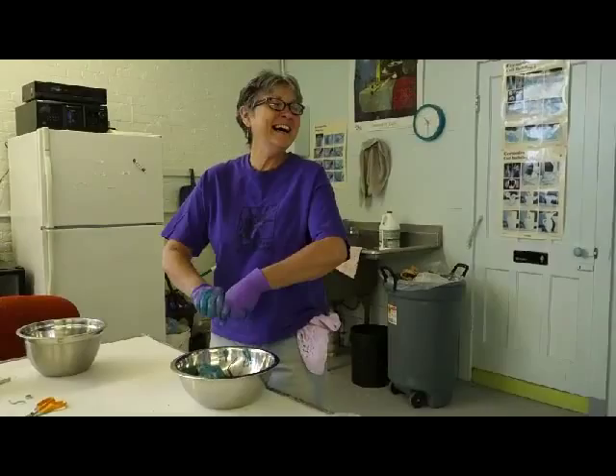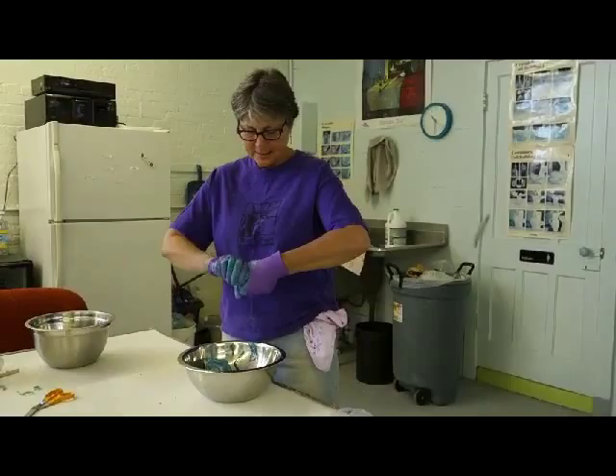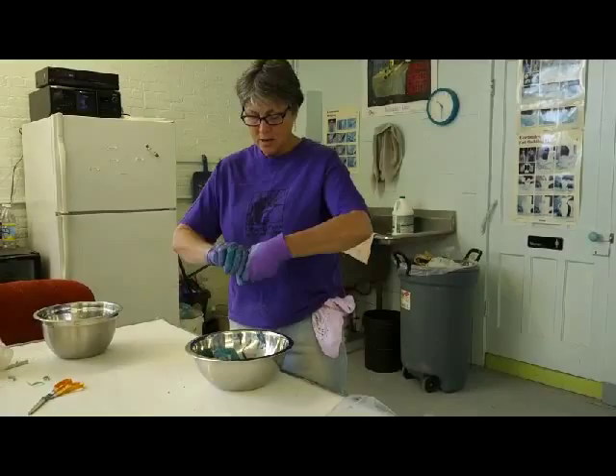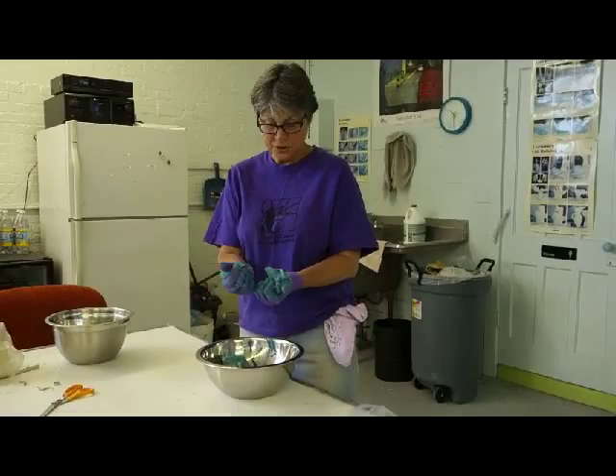It's pretty much just wedged in until you get it all the way through — it's like the best bread you've ever made. Some colorants, some stains and oxides such as cobalt carb and cobalt ox will have little pits, little pieces of color that take a long time to dissolve. Those really should be ball milled.